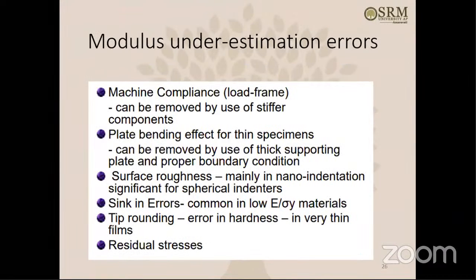Then as we talked about overestimation, sometimes it is underestimation. So the modulus is underestimated in the sense that the correct value is supposed to be 70 GPa, but sometimes it is coming as 40 GPa or 30 GPa or 20 GPa, like the underestimation. So what could be the errors for underestimation? So machine compliance, that is the loading frame. The loading frame has certain compliance, okay, and something gets lost in that compliance. So it can be removed by use of stiffer components, but of course it's not possible every time.